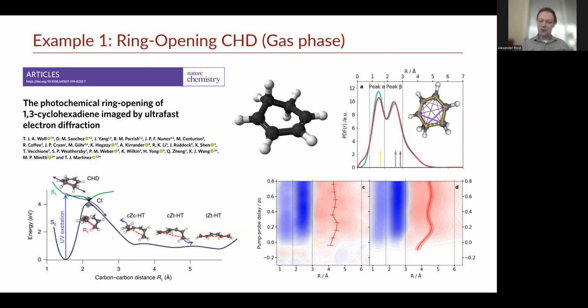So first of all, going over to the photochemistry side, this is a great example of the type of measurement that we've been doing on cyclohexadiene. Using a gas cell inside the chamber, we're able to explore chemical reactions initiated by a laser pulse. In this case, the CHD molecule, upon UV excitation, has its carbon-carbon bond broken. And so then the structure evolves and the molecule stretches out over time. MeV-UED allows us to follow this in real time through this process. And this then can be used as a benchmark against quantum simulations of this process. And you can see here, lower panel, that the data and simulations match up really well.